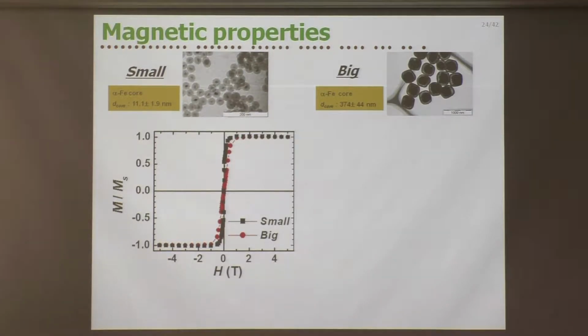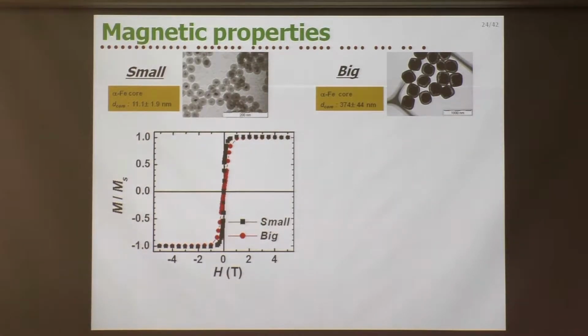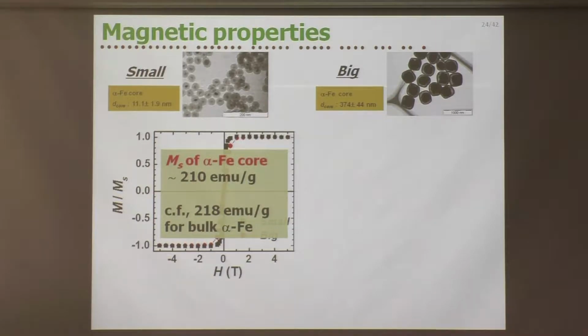Now I'd like to talk about the macroscopic magnetic properties, again for the small and big samples. Here shows the hysteresis loops measured at room temperature. These are normalized, but we can estimate the saturation magnetization of the alpha iron core. Its value was about 210 EMU per gram, which is very close to the literature value for bulk alpha iron. So with this data, we can also say the formed nanoparticle is very good alpha iron.